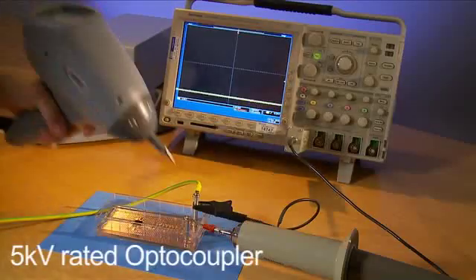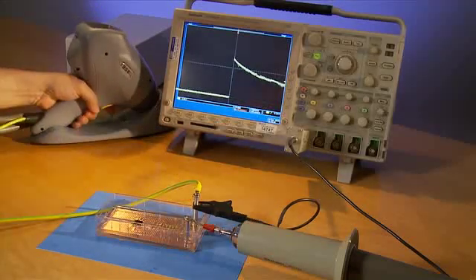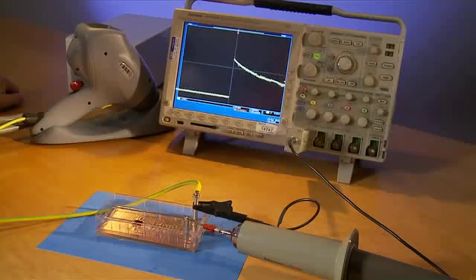Now let's surge a 5 kV rated optocoupler. It passes the 10 kV requirement, and the pulse looks similar to the open-circuit case, so the insulation is intact. Polymers do well in surge environments.